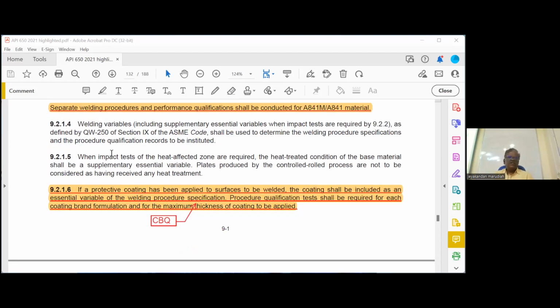So highlight this one. If a protective coating has been applied to surfaces to be welded, the coating shall be included as an essential variable of the welding procedure specification. Procedure qualification test shall be required for each coating brand formulation and for the maximum thickness of the coating to be applied. So you have to consider that also an essential variable. You have to apply it during the PQR test.